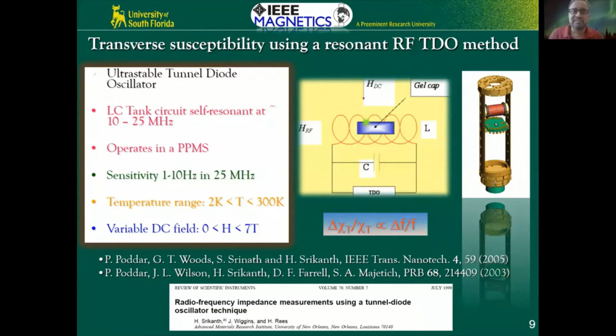The sample sits inside here, and of course this whole thing goes into a superconducting magnet, the PPMS that I discussed earlier. So that's, for example, how the PPMS sample probe looks. This is our coil right here. The transverse geometry is because the DC field supplied by the magnetometer, the PPMS, is perpendicular to the small modulating RF field on the sample, and that sets up this crossed field geometry, from which we can extract the transverse susceptibility.